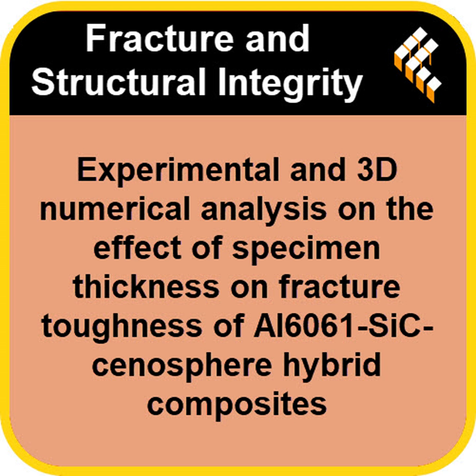That's the gist, yeah. First, you use a special machine, a servo-hydraulic fatigue machine, to create a fatigue pre-crack. This gives you a very controlled, sharp, consistent crack tip, simulating a real-world flaw. Then you apply what's called monotonic loading. Basically a slow, steady pull until it breaks. You measure the critical load, P_Q, and use that to calculate the conditional fracture toughness, K_Q. Right, and this brings us to maybe the most critical finding in the paper, the bit that translates directly into engineering design, into safety. What happened when they plotted that toughness, K_Q, against the thickness, the B/W ratio?